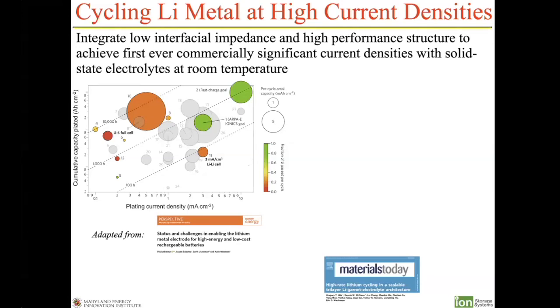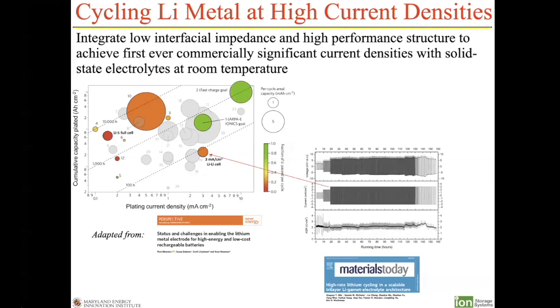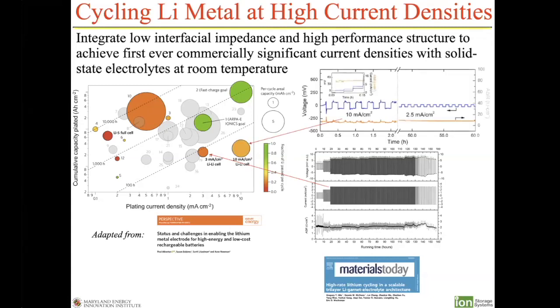And you can see there's just a few orange or yellow, red data points in the literature as far as lithium cycling. The one that's at the highest current density in his paper is reference 11, and that in fact was our work, because at the time he was my program director. But since then we've exceeded that, as I showed you, with 10 milliamps per square centimeter. So as far as I know, we're the only group that's achieved both the ionics and vehicle technology fast charge goals for current density for lithium cycling at room temperature. I do want to point out again the room temperature aspect of this. We can cycle even faster at higher temperature, but this is at room temperature.